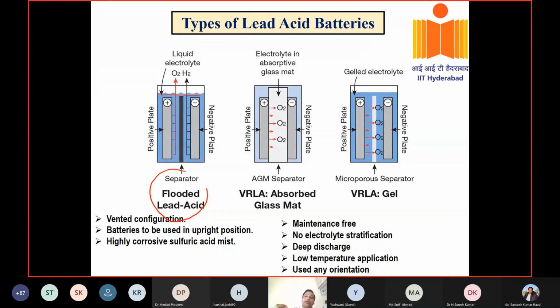So the oxygen and hydrogen evolve during charging and escape, and the electrolyte concentration changes. That's why you are topping up with water. And the problem is that, if it is a closed room, you have corrosive sulfuric acid mist which is evolving from the battery always. It's not good. So when you keep a flooded lead acid battery, you should keep it in a ventilated position.